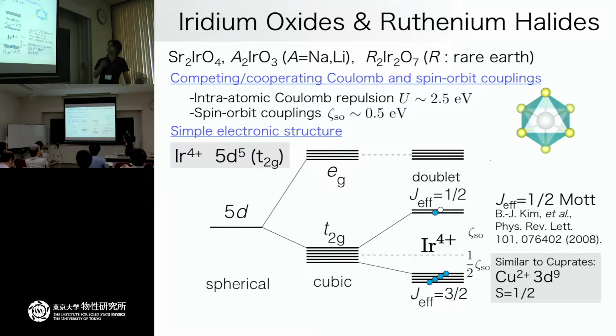If you look at the t2g manifold in this oxide, and if you write down some ab initio effective Hamiltonian for the t2g manifold, then you can figure out that the intra-atomic Coulomb repulsion in this system is around 2.5 electron volts. It's compared with the large spin-orbit coupling, which is roughly 0.5 electron volts.